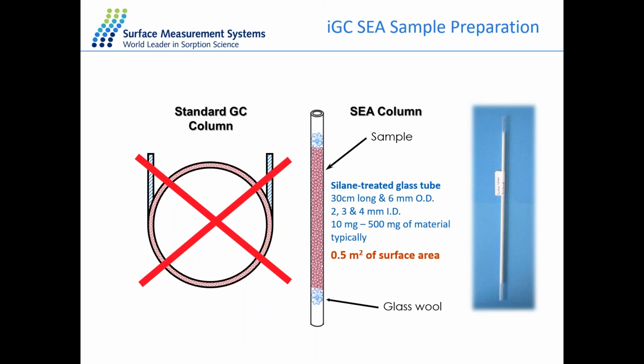So with regards to contact angle, you can compare the surface energy results as long as you're using the same types of probes. So the same polar probes and non-polar probes. However, with the contact angle experiment, you're limited to the probe molecules, and also you're only looking at localized areas of the surface of your sample. Whereas with the iGC-SEA, we can actually inject different percentages across the surface of your sample. So we are able to look at the whole sample rather than small localized areas.